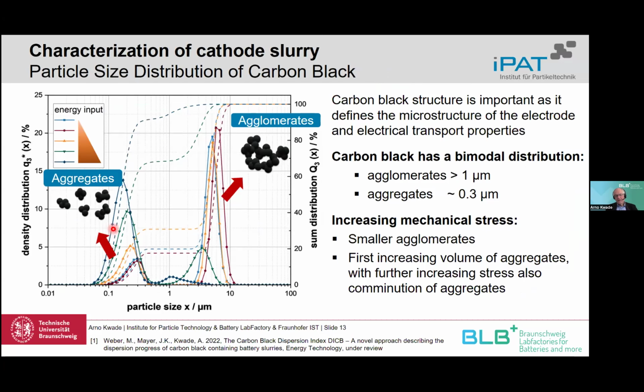But we are looking for another parameter which we can also use for quality control during the processing, especially already during the dispersing of the particles. And it's not so easy because you have bimodal distributions of the carbon black. I mean, the active material shouldn't change, otherwise you have a degradation of them. So we have to measure the carbon black. We defined a way to measure the carbon black distributions by some centrifugation and certain laser diffraction measurements. And you see then this very strong bimodal distribution.